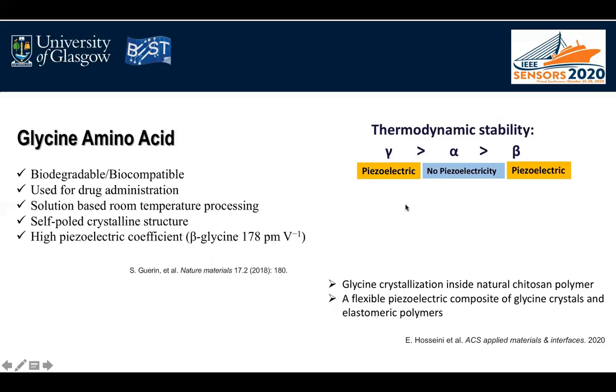However, beta-glycine crystals are brittle, and the beta phase, which has the higher piezoelectricity, is thermodynamically unstable and usually co-crystallizes with other phases of glycine like alpha and gamma. That's the reason they have not been much explored for sensing device applications. But here we could fabricate a composite of glycine with the natural polymer chitosan, and these composites have enough flexibility and are stable, and that's why we were able to fabricate a sensor from that.